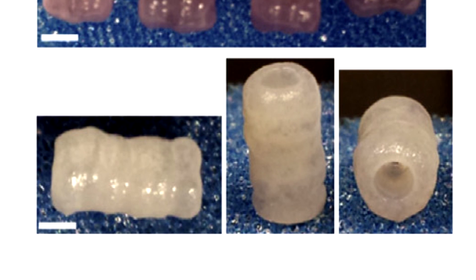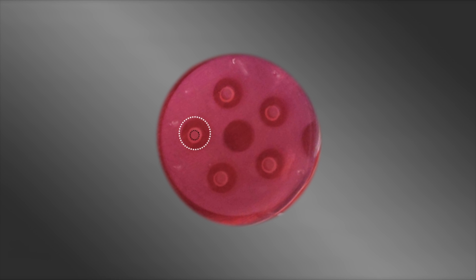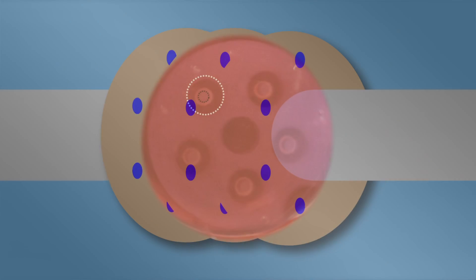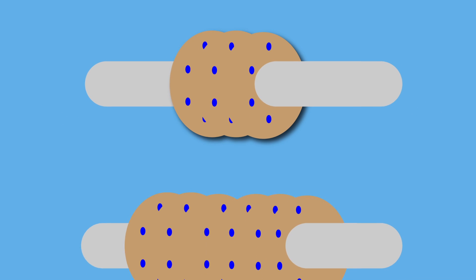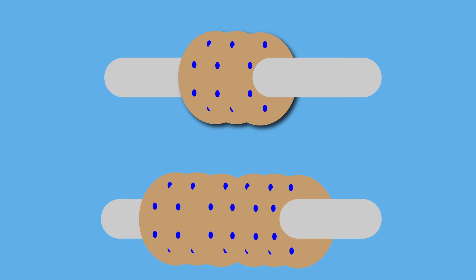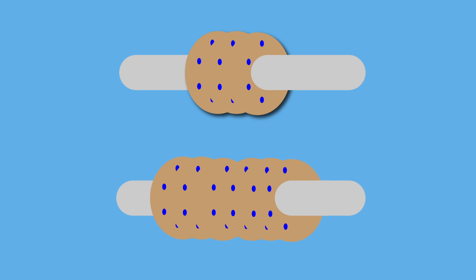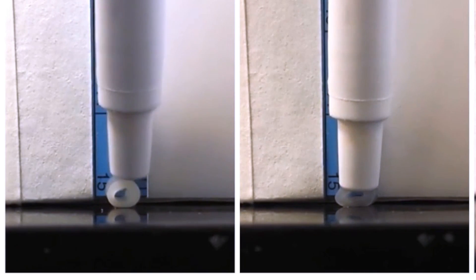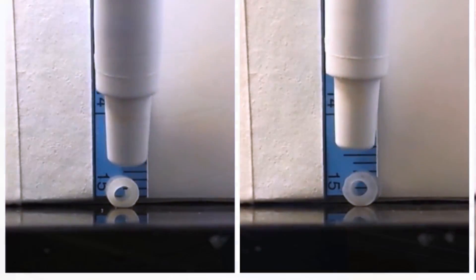Oftentimes, due to disease or injury, the trachea will stenose or be closed off. We're using molds to form donut-shaped mesenchymal stem cell constructs to engineer the trachea, and delivering signals within these donut constructs. By stringing constructs onto a tube, these donuts will fuse to form cylinders in the shape of the trachea. These tissues have the mechanical integrity similar to that of the native trachea.